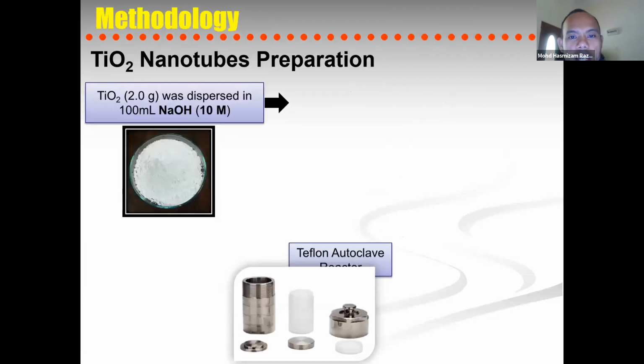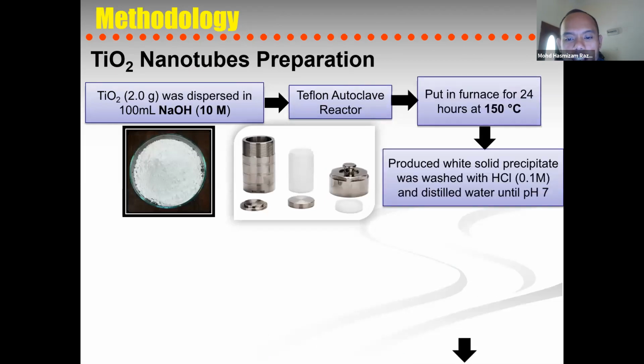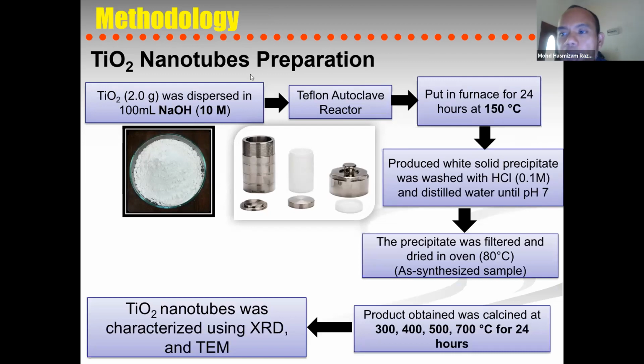So how do we prepare titanium dioxide nanotubes in our research? We use a hydrothermal method. We have commercial TiO2 mixed with sodium hydroxide and put in an autoclave, and then the mixture is put in the furnace for 24 hours. Then it is washed with HCl and distilled water, and dried at 80 degrees C. Finally the product is calcined at 300, 400, 500, and 700 degrees C for 24 hours.